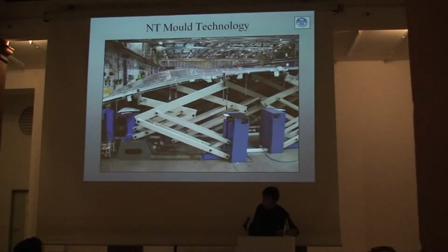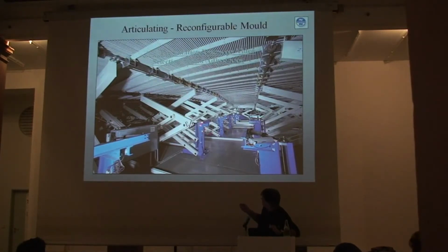That's a look at the mold technology that you saw in the video a little bit. So again, adjustable surface here with a nylon covering on it, metallized nylon covering. Pultruded fiberglass running in the 0 and 90 axis underneath the mold. None of that fiberglass is actually fixed to the surface of the mold, because as the mold adjusts into an aerodynamic shape, it has to grow or it has to shrink. So those rods aren't fixed, and you can see the lifter armatures here that are driven up and down by a vertical worm screw that is attached to 2 pneumatic actuators. So 2 pulses of each actuator drives the vertical worm screw around, which lifts the pantograph lifters up and down in the z-axis in vertical space.